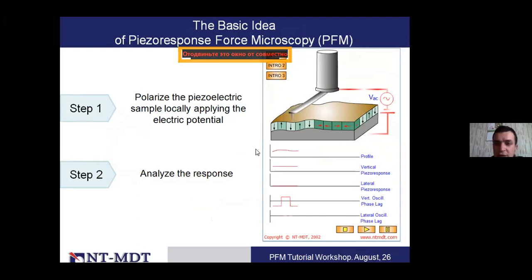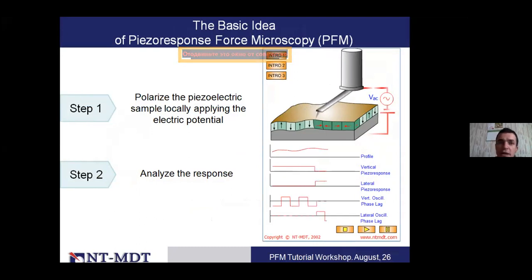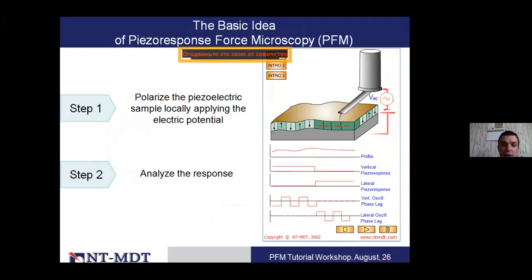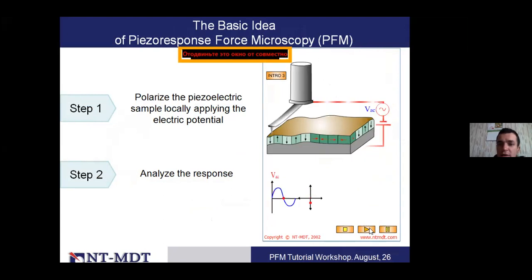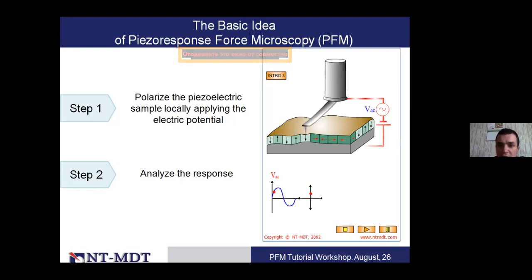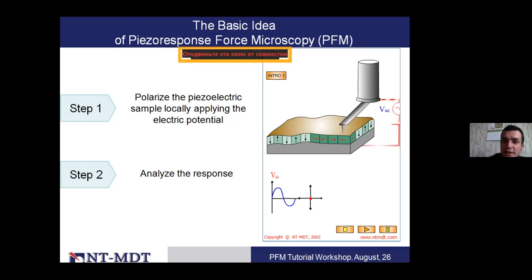Another interesting measuring mode is called piezo response force microscopy, PFM, and it allows us to measure the piezo effect properties on piezoelectric material. This technique is operated in contact mode. So we stay in contact with the surface, and then we apply an alternating voltage between tip and sample, and the tip should be conductive. Depending on the piezoelectric properties of the surface, we will have a different response on the cantilever. By measuring this response, we can understand if it's higher or lower, or left, right, or up, down. We can understand what the piezoelectric domains on the surface are.